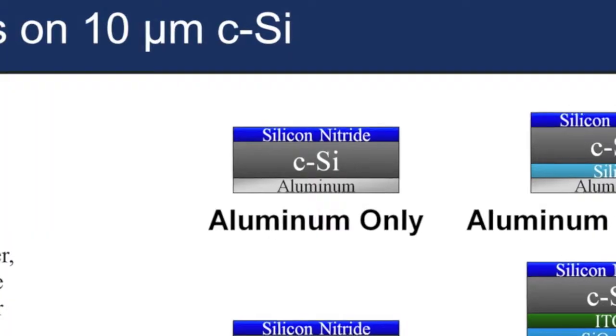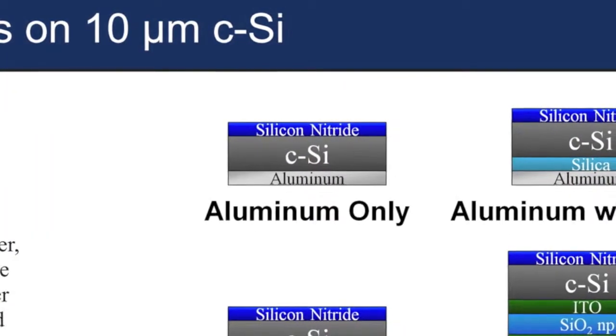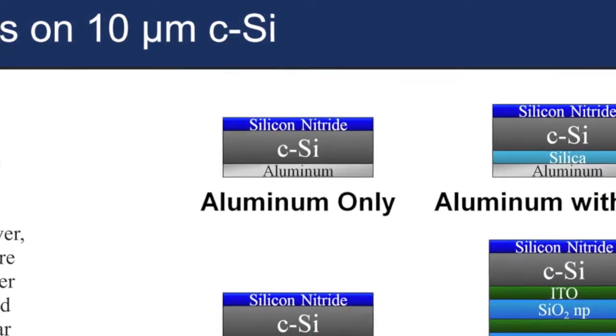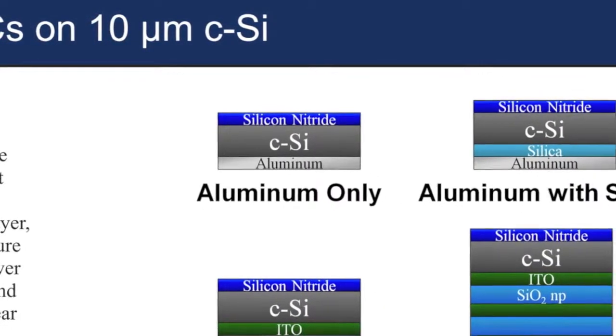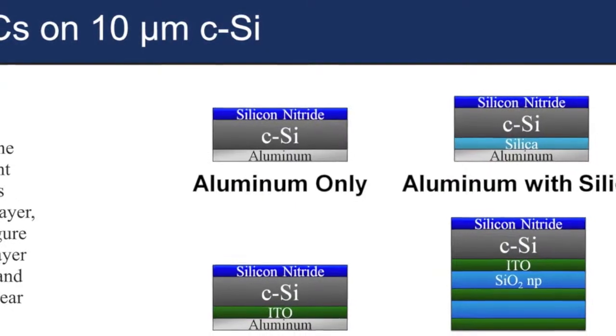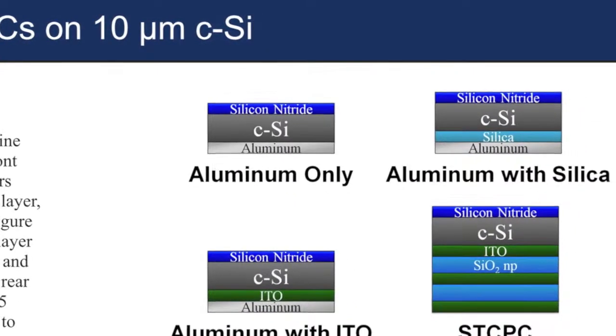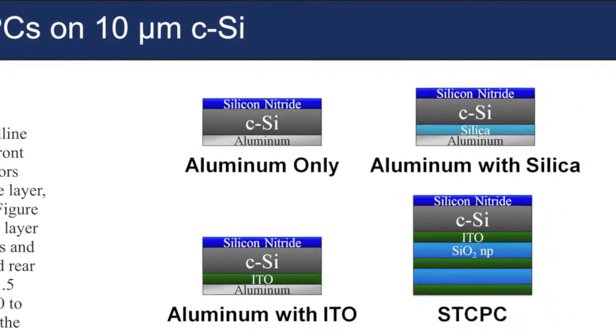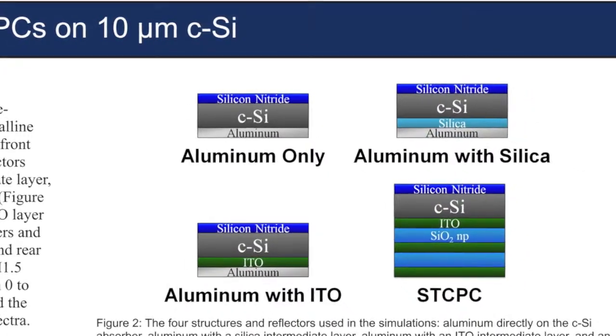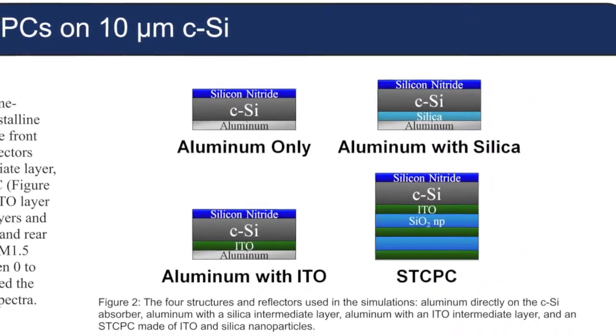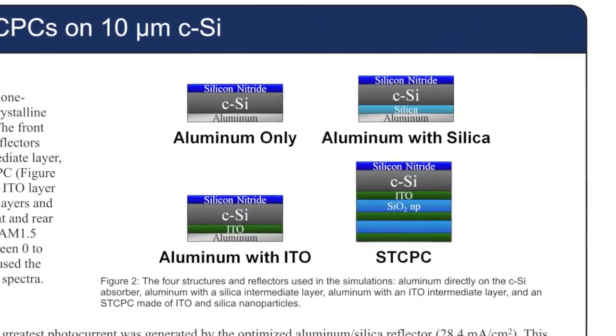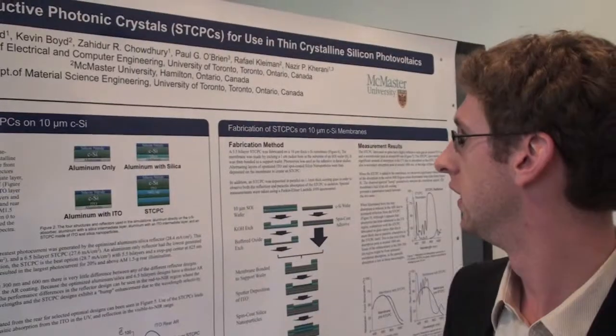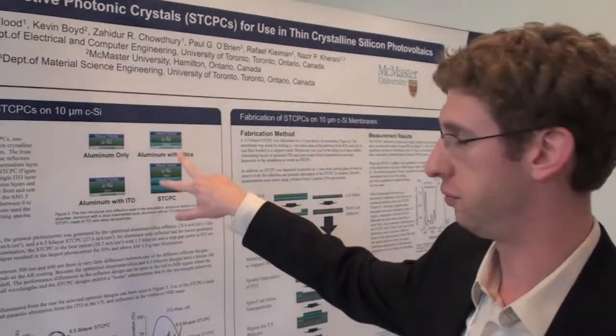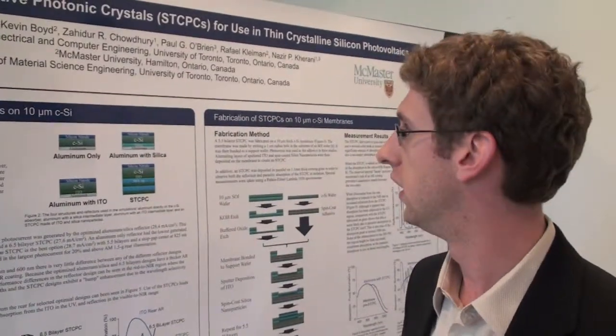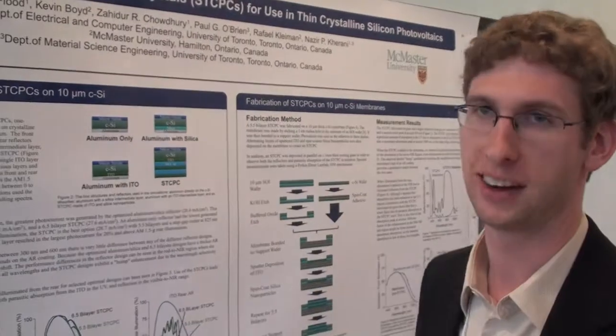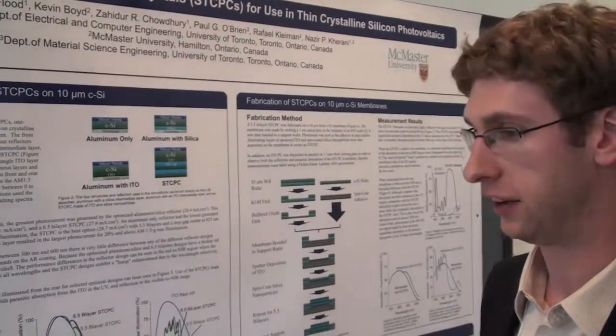In particular, we considered a silicon membrane with just an aluminum reflector right on the silicon surface, an aluminum reflector with a silica intermediate layer, with an ITO intermediate layer, and also when we use a selectively transparent and conductive photonic crystal, which is the reflector I was referring to before. The reason to use the intermediate layers is because we know these are optically preferable to an aluminum reflector just on the back, but they can be more difficult to fabricate.